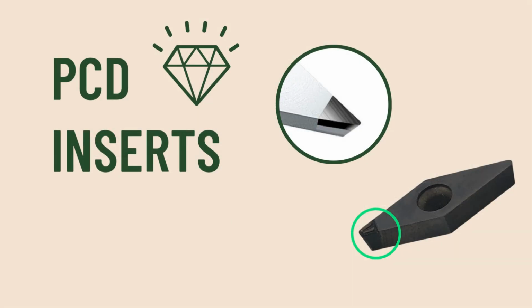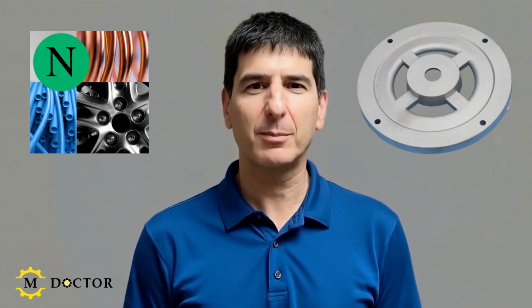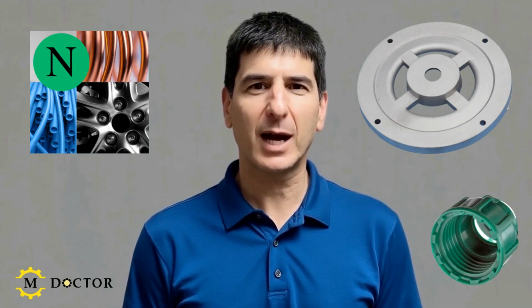The next cutting material we explore is PCD, the hardest cutting material available. It's a synthetic diamond, created by sintering diamond particles with a metal matrix, under extreme temperature and pressure. The result? A material that's 90 to 95% diamond, reaching hardness levels near 6000 HV. Because of its extreme hardness, PCD is very brittle, even when compared to other advanced cutting materials. This brittleness restricts its use to softer materials, such as non-ferrous. Aluminum is the main application, followed by plastics and brass.